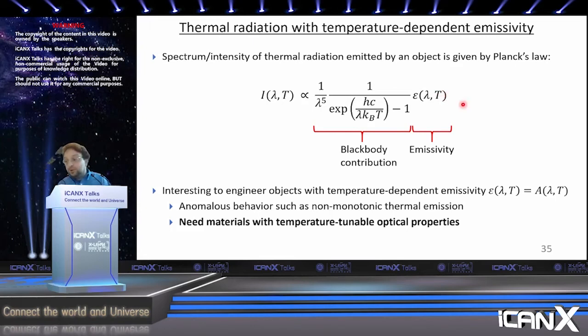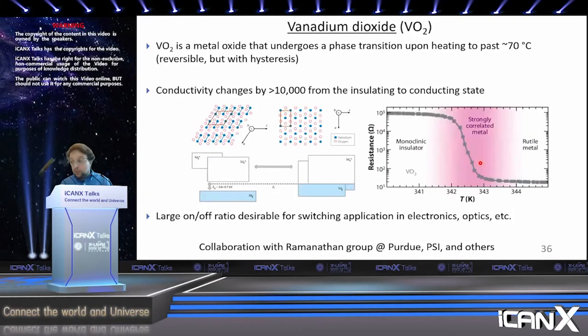And if you want to be able to do this kind of engineering, you need materials with temperature tunable optical properties. So essentially, you need materials whose complex refractive index changes a lot with temperature. And so what we've been using as a building block for these thermal radiators is a class of materials that undergo insulator to metal phase transitions. And the most famous example of this is vanadium dioxide.